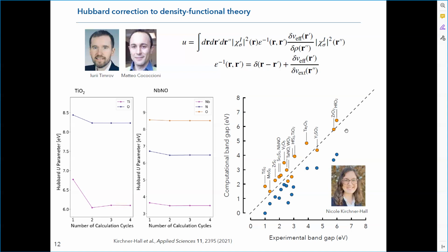So you see on this benchmark that contains chalcogenide, oxynitride, oxide, we get a fairly good agreement between the computed band gap and the experimental band gap, with a slight tendency to overestimate the band gap. So this is probably the result of having fixed orbital, and because of that, of over-localizing the electron and overestimating the self-interaction corrections that we have in that case.